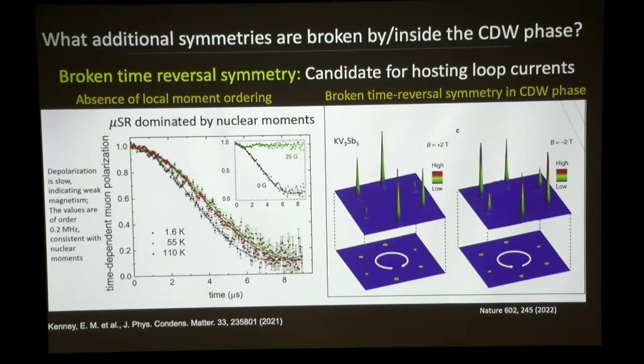The first studies were done by STM. So what they did is the following. These are the six CDW peaks. As I pointed out already, they actually have different intensities. So this one is least intense, this one is most intense. And this work, done by Zahid Hassan, showed that the intensity of these peaks is sensitive to a magnetic field. So at +2 Tesla, this is the highest peak. At -2 Tesla, you see this one is higher than this. So the relative intensity of the charge density wave peaks can be manipulated with a magnetic field.